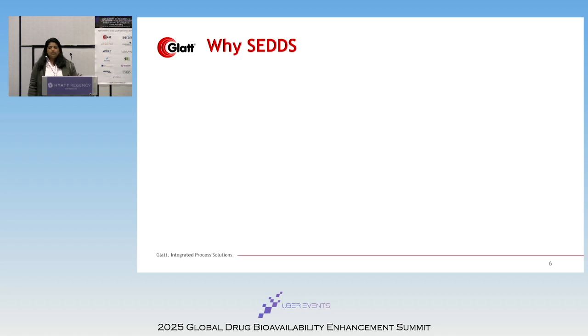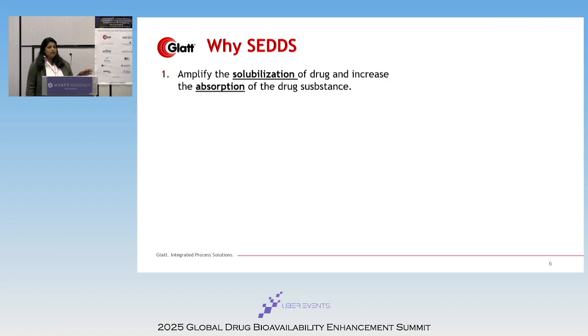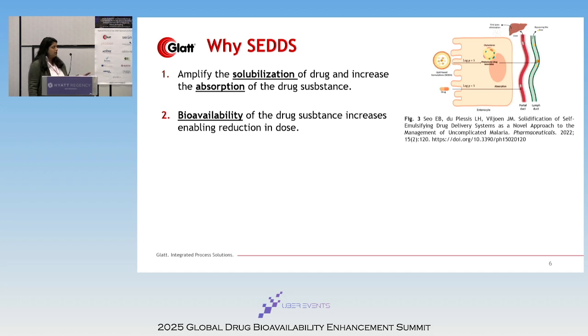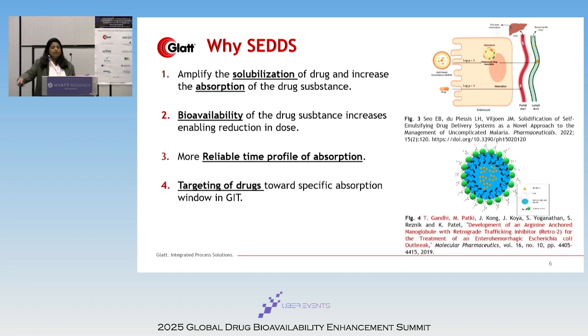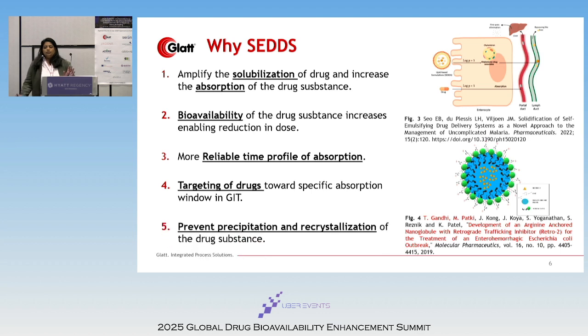So why SEDDS? Because it increases solubilization, and that is because of the fine droplets and the increase in interfacial surface area. But they also create a lipophilic ambience, which increases the absorption of the drug through the intestinal absorptive sites, thereby bypassing the first-pass mechanism, so we are increasing the bioavailability too. They also have a consistent and predictable absorption time profile, which is reliable. Then coming to targeting of drugs, I have my own published paper where we talk about how we can target these cells to a specific site to treat a specific Escherichia coli in the intestine itself. It also prevents the precipitation and recrystallization of the drug substance.